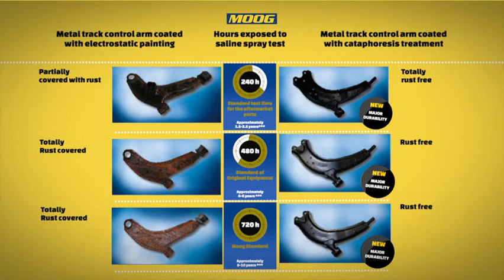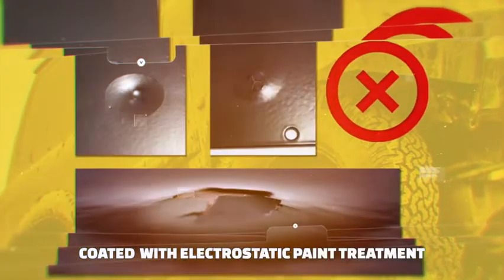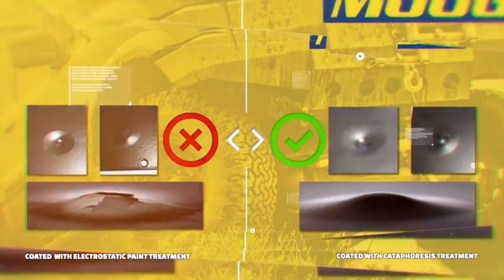On the other hand, in the process of cataphoresis, the piece is immersed in the paint, also electrically charged, so this is able to cover the hidden areas of it. So the internal cavities and holes of the piece are also protected against corrosion, preventing rust from starting from the inside of the metal part. With the cataphoresis technology, MOOG offers a much better product with excellent protection against corrosion. The paint is thicker and more elastic, so it does not crack, offering a much longer product life in optimal conditions.